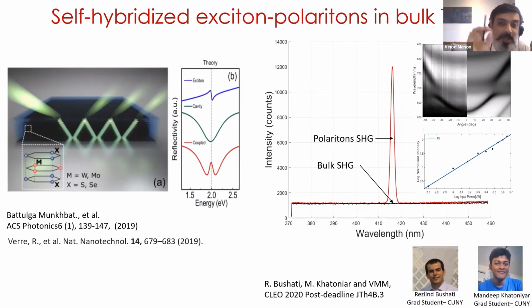So this is not in the monolayer limit, and that's a key aspect. You have to do a few layer system, so it doesn't emit light. Nevertheless, it still absorbs light. But if you create the thickness of this layer to be the right thickness, then you can create a Fabry-Perot mode between these two interfaces, and you can get the light to get trapped inside the system, and essentially it forms a Fabry-Perot resonance.